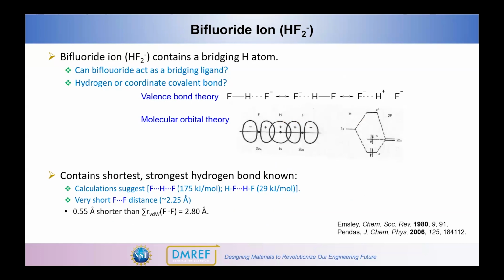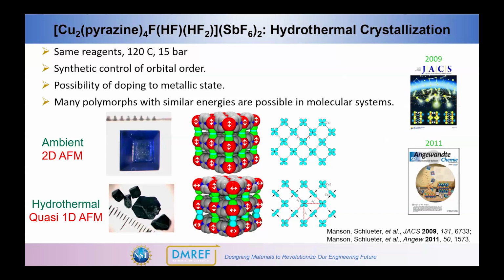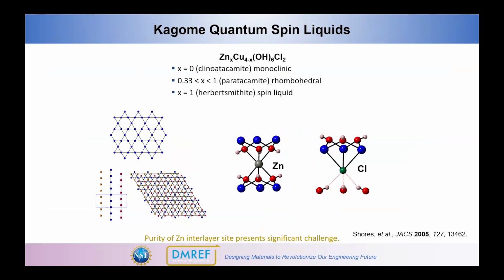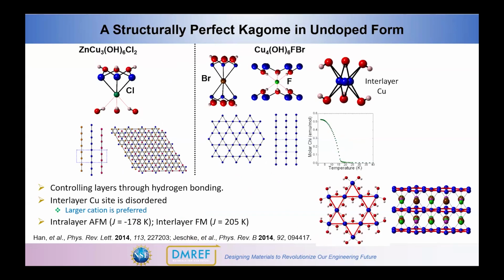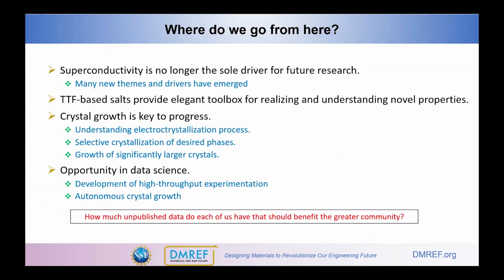And we have some work here on the bifluoride ligands, which I'm not going to really be able to explain other than the fact that by controlling the synthetic conditions, you can either make a phase where all the Jahn-Teller axes are aligned in one direction or where they alternate, like along Z and along X, and that has implications on the magnetic properties as well. And I'm probably going to skip this one for the matter of time as well, but it's basically putting fluoride into the Herbertsmithite type structure to be able to control the packing.